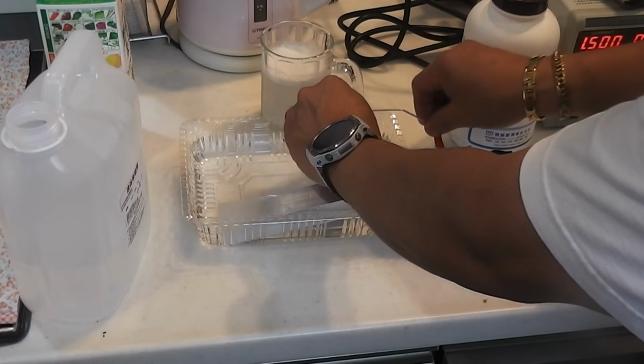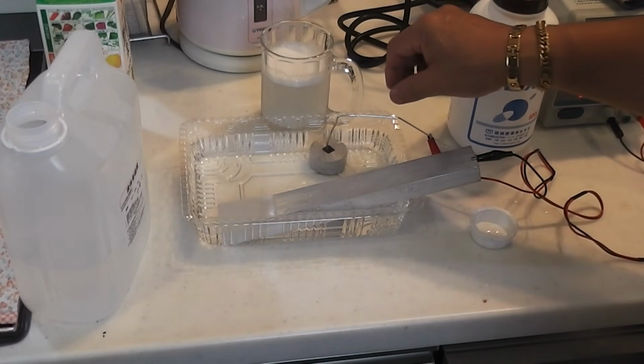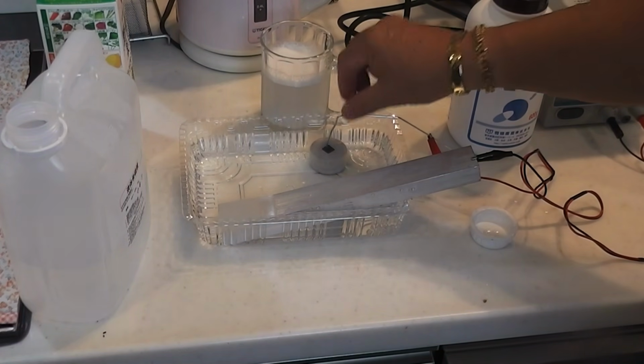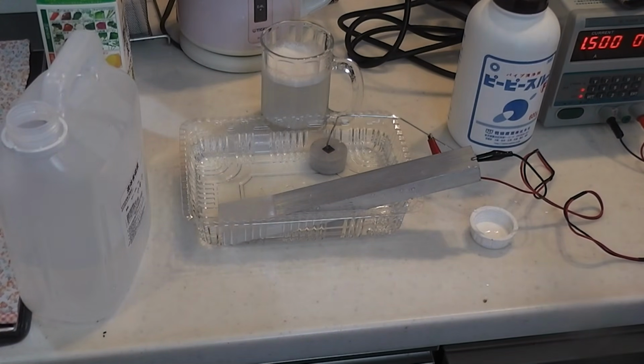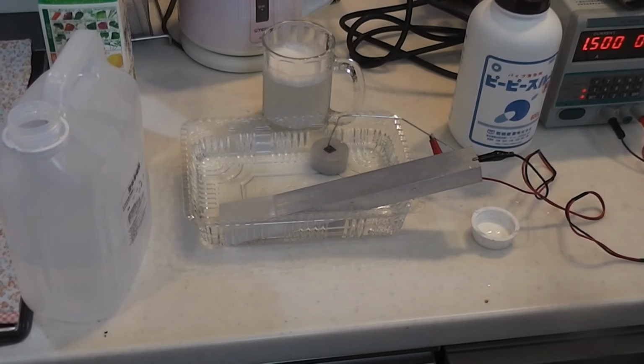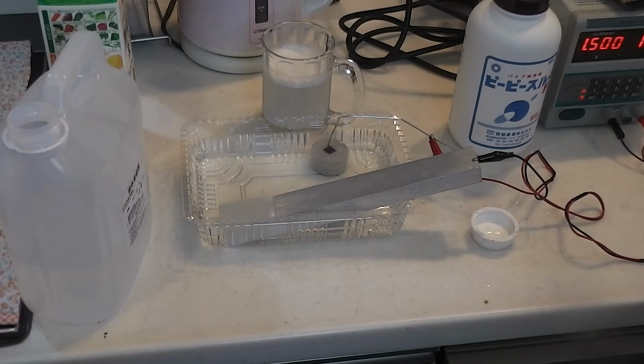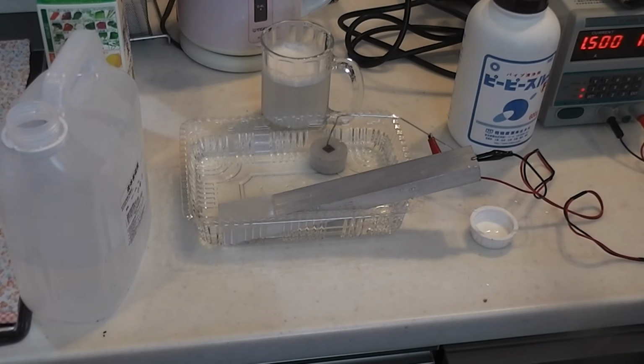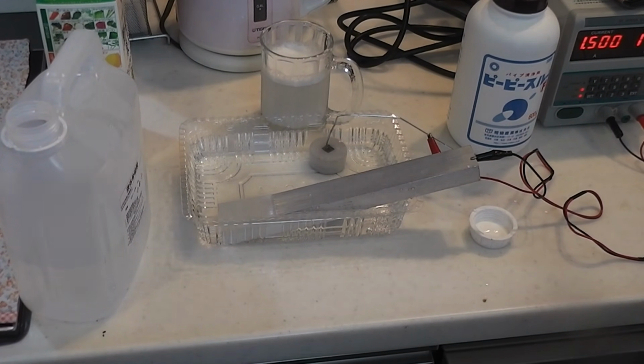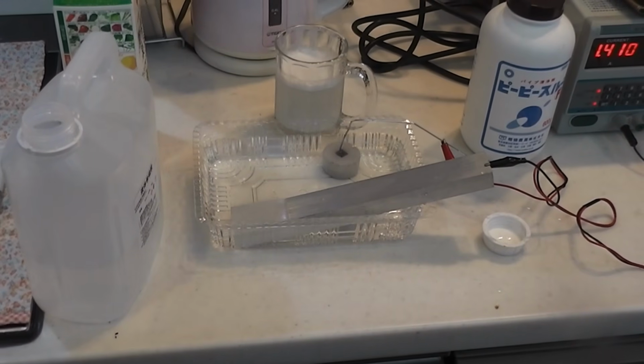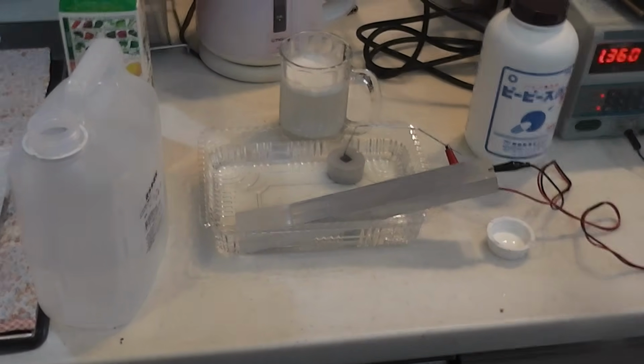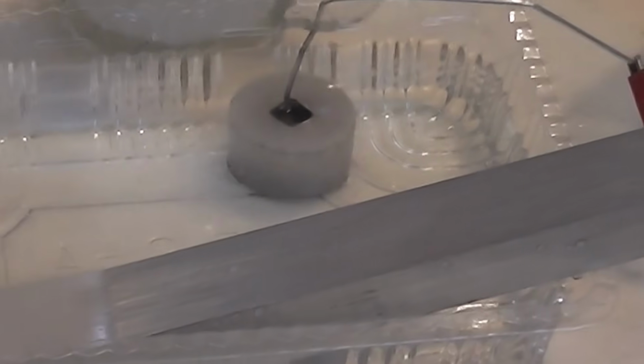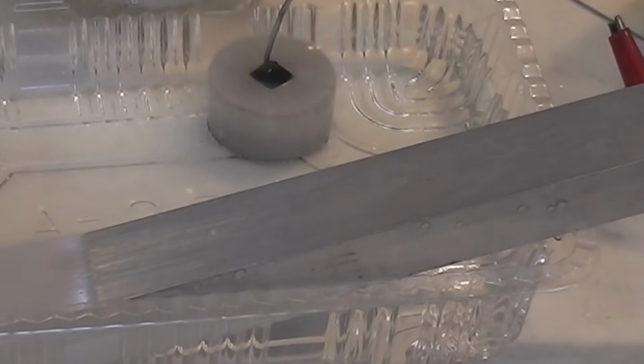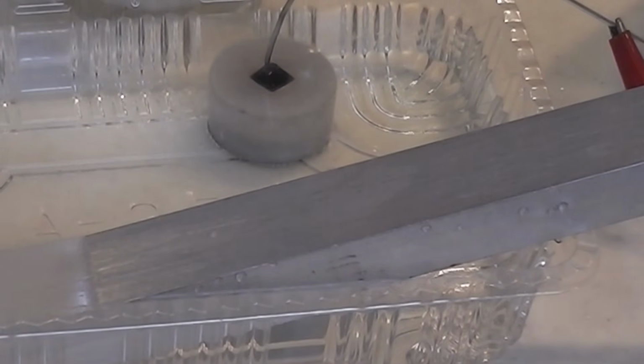Now, the chemistry begins. As electrical current flows through the electrolyte, oxygen atoms combine with the aluminium surface to create aluminium oxide. Unlike rust on steel, which weakens the metal, aluminium oxide is extremely hard and actually protects the material underneath. At the same time, sulfuric acid slowly dissolves tiny portions of the newly formed oxide. These two reactions happen simultaneously. One reaction builds the oxide layer. The other creates millions of microscopic pores throughout its surface. This balance is exactly what makes anodizing possible. Without those pores, the aluminium couldn't absorb any color.